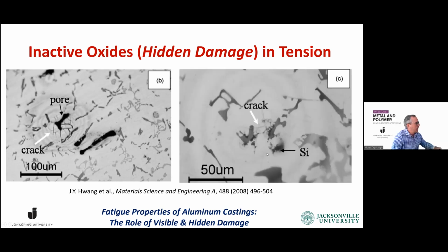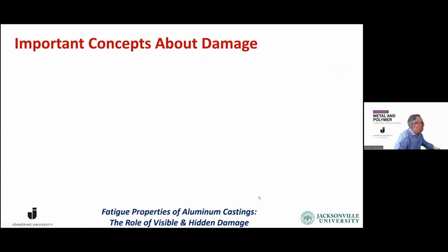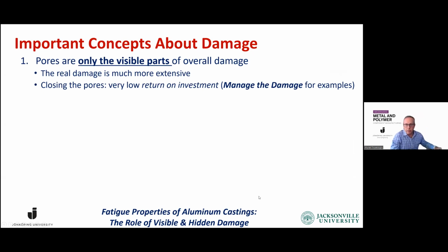Here's another one. And again, in this case, there's a silicon particle, but there are cracks in the structure. And these oxide films, the inactive oxides or the hidden damage, now start presenting themselves. It's no longer hidden because it cannot withstand the tensile stress. So the important concepts about damage that we want to emphasize are that pores are only the visible parts of the overall damage. The real damage is much more extensive.